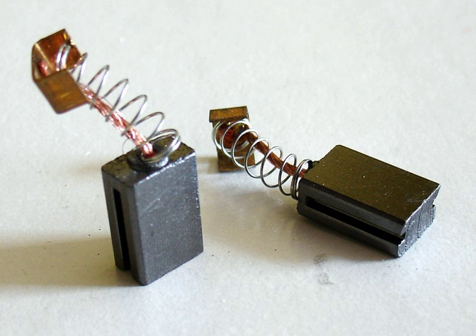The brush compound is compacted in a tool consisting of upper and lower punch and die, on mechanical or hydraulic presses. In this step, depending on later processing, the copper wire, called shunt wire, can be inserted automatically through a hole in the upper punch and fixed into the pressed brush block by the powder pressed around. This operation, called tamping, is usually performed using electrolytic copper powder, possibly with silver coating for some high-performance applications. After this process, the brush is still very fragile and in professional jargon called a green brush.